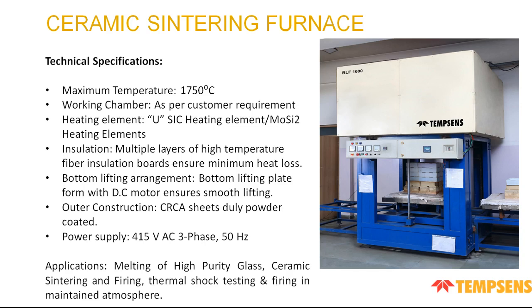This is used for sintering of ceramics at high temperature, maybe around 1750 degrees centigrade, and for 1400 degrees centigrade we can use SiC heating element, and for higher temperature above 1400 degrees centigrade we use molybdenum disilicide heating element. And there can be multiple layers of high temperature ceramic fiber boards plus brick arrangement used to avoid the heat loss, and there will be a bottom lifting platform with a DC motor used in that too for smooth lifting of the material.